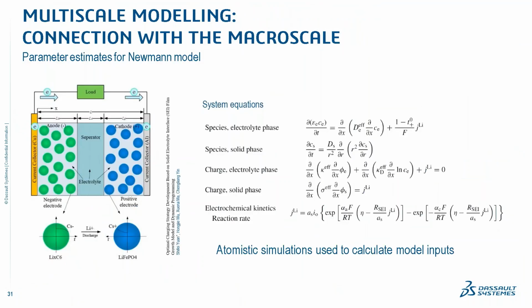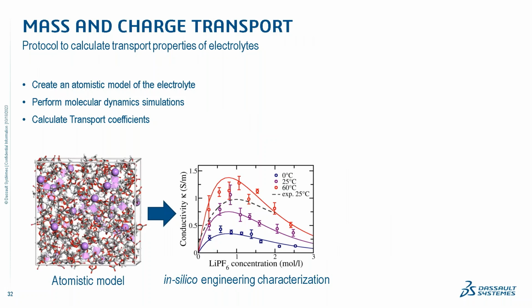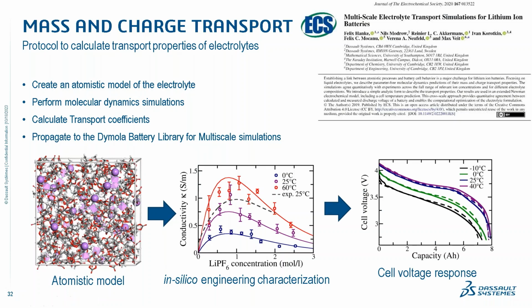And one way of doing that is that in the Newman model, there are a number of material properties. These can be determined then from atomistic simulations. So for instance, here we have an example where we did molecular dynamic simulations for electrolyte as a function of the salt concentration and temperature variation to derive this curve, the conductivity as a function of lithium concentration. This information could then be ported up to the Dymola Battery Library to perform simulations then of capacity voltage curves at different temperatures to see how that behaves in a cell, which shows good agreement with experimental data.